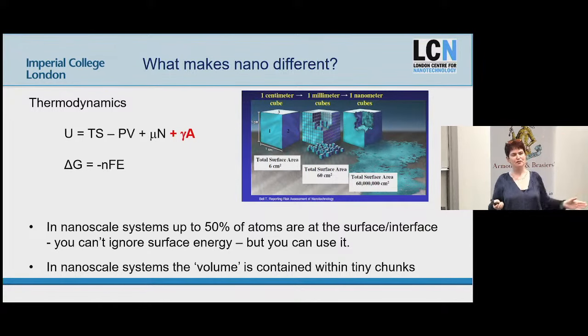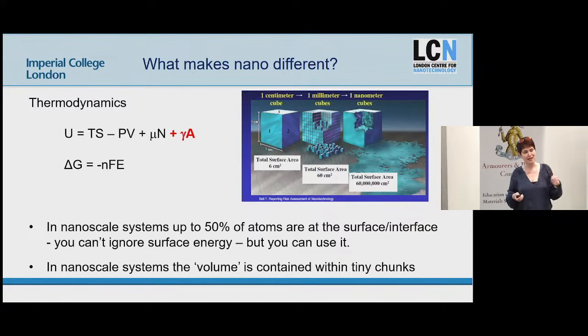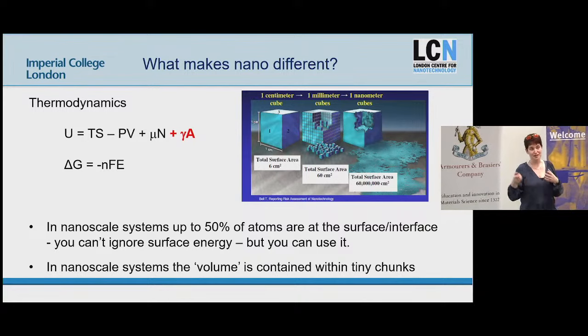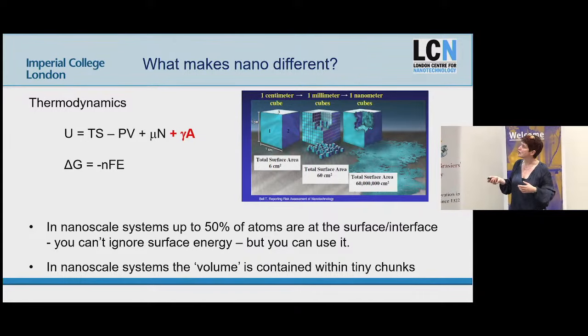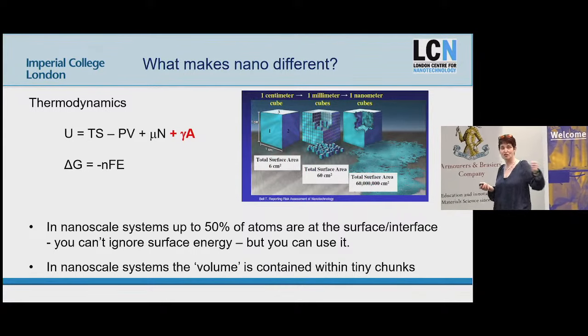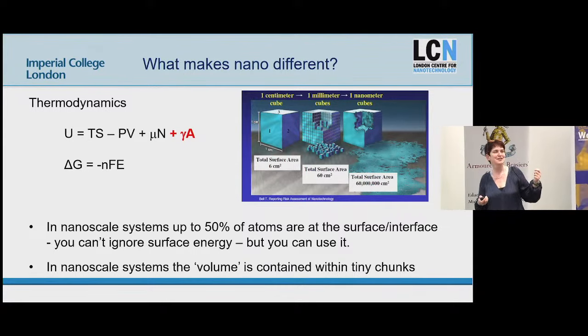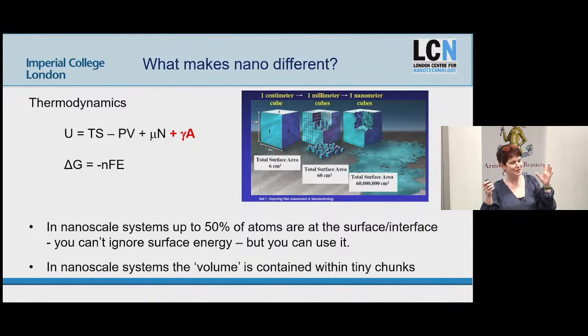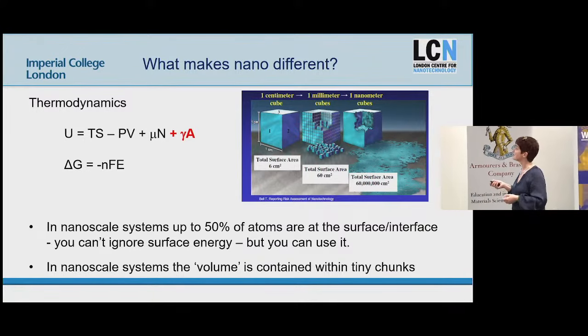That number is shifted when it's a nanomaterial. So it behaves and it reacts very differently than if it's in the bulk state. As a general idea, if you think of a nanoparticle, something like 50% of the atoms in a nanoparticle are at the surface or in a surface site. So it's behaving very differently. It's not surrounded by lots of nearest neighbors. It doesn't have very many friends, right? It's sitting on the surface, disconnected, and in a high energy state.